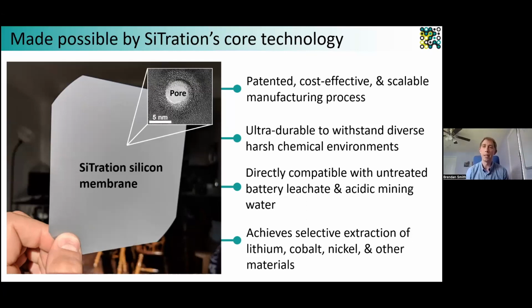We're now exclusively licensing that IP back for SiTration, which is a very common practice with things invented at universities. And the two-step process essentially involves existing processes assembled in a very strategic way. So the first step is a very simple metal deposition approach. So we basically blast a bunch of metal onto the surface. This metal becomes a catalyst in the second and final step, which is a chemical etching process.